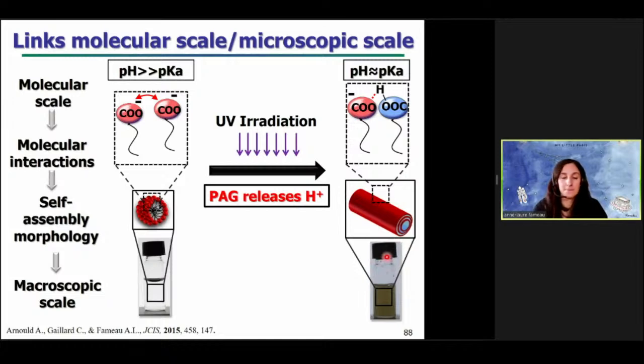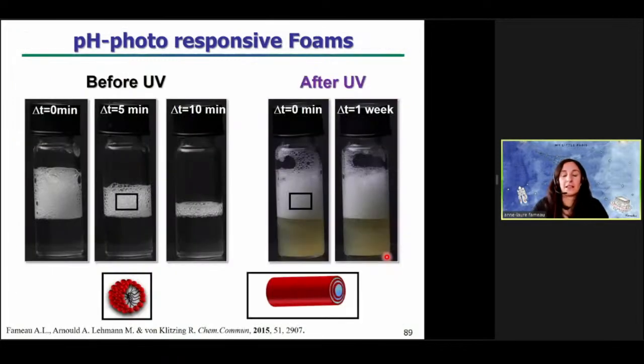Then we determined the foaming properties of this system. So before UV radiation, we have spherical micelles. You observe very fast foam destabilization. The spherical micelles can't stabilize the foam. But after UV radiation, tubes are formed inside the foam, and we observe very stable foam again. So in this case, we obtain pH photoresponsive foams, so we can stabilize foams that were previously unstable just by the application of UV light.